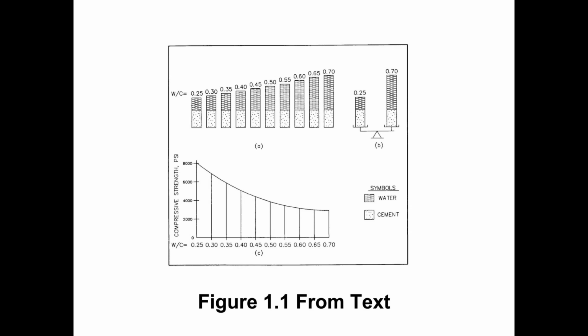So after each of these samples are cured, they've fully reacted and any excess water has been removed. When we weigh those samples, what we should find is that they weigh the same. So even though we started out with varying amounts of water, since we started out with the same amount of cement for each sample, that same amount of cement will react with the same amount of water, and so we end up with a sample that weighs the same.